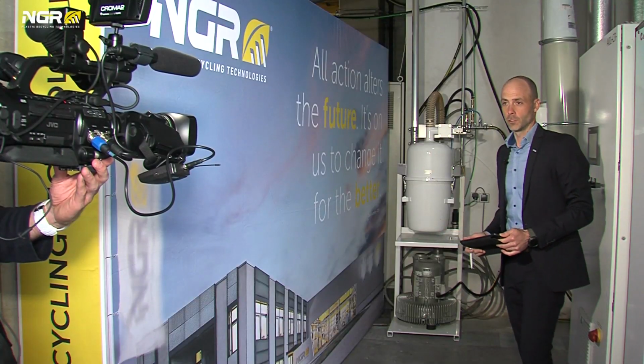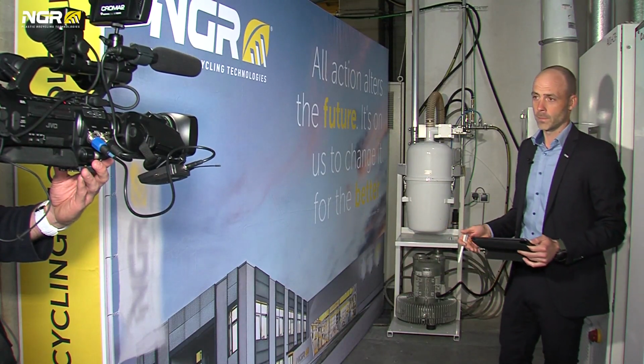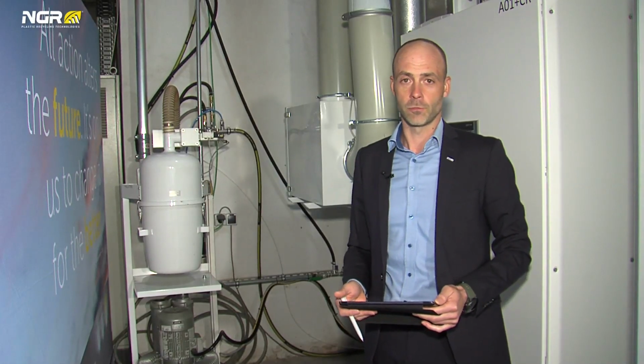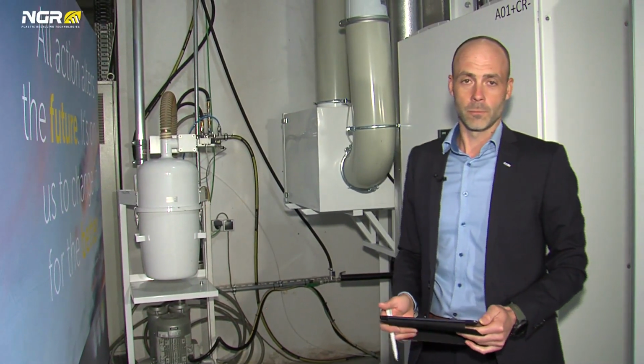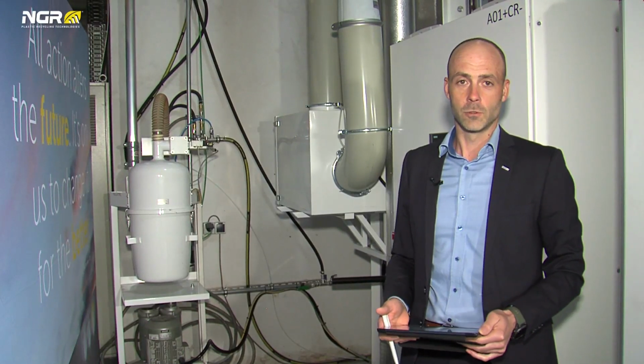The humidity is the biggest enemy of PET because it leads to high IV degradation during the extrusion process. To avoid this degradation, we pre-dry the bottle flakes before they enter into the extruder. Starting with the crystallizer, where we process the material for approximately 1 hour. The crystallizer is equipped with an agitator to avoid agglomeration of the pre-dried material. The level sensor on the top of the crystallizer gives the signal for the start and stop of the material conveying.